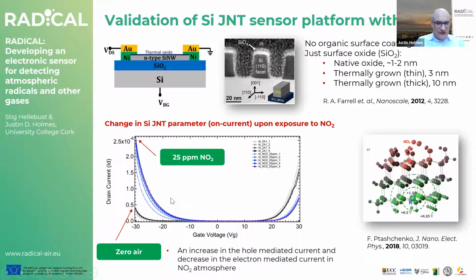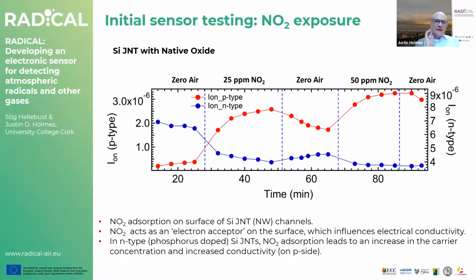And you can see in the presence of 25 parts per million NO2, we see a signal, and then in 0, where we see a lower signal. So we're now starting to see an increase in this current, hole-mediated current, when we have an NO2 atmosphere. So can we use this as a sensor? And these are the initial sensor tests upon NO2 exposure.